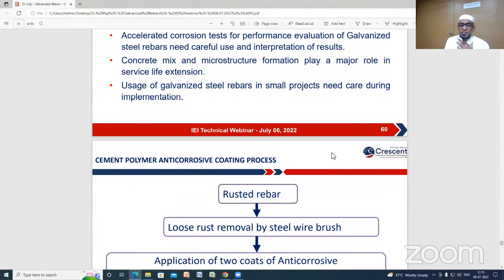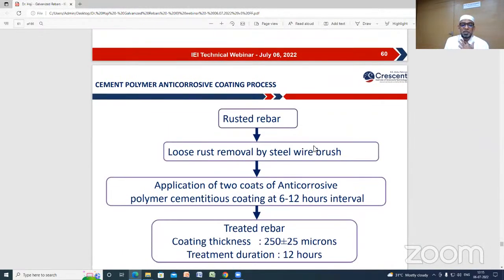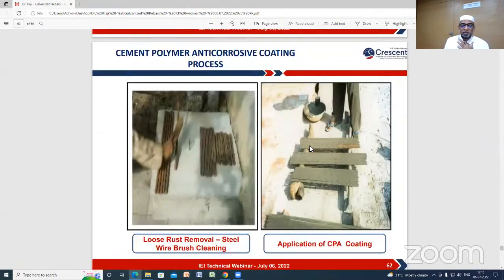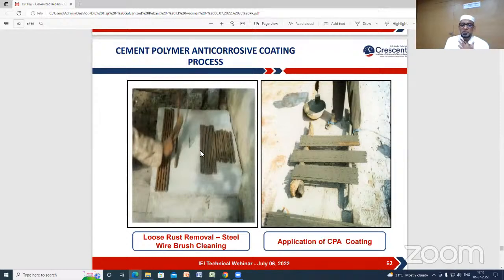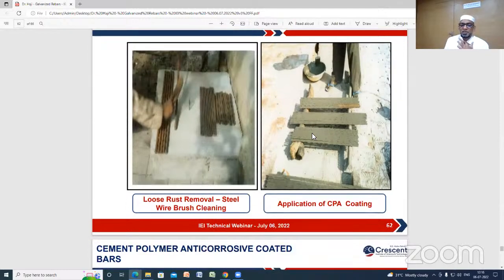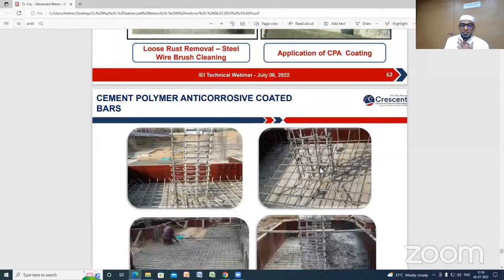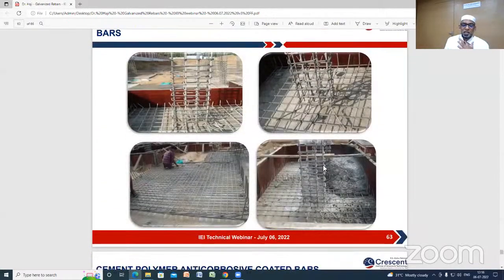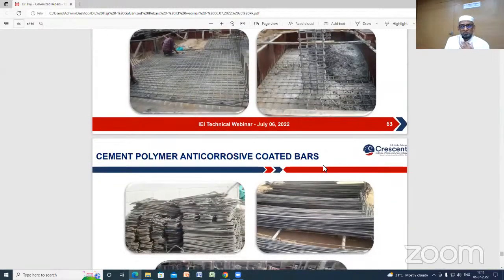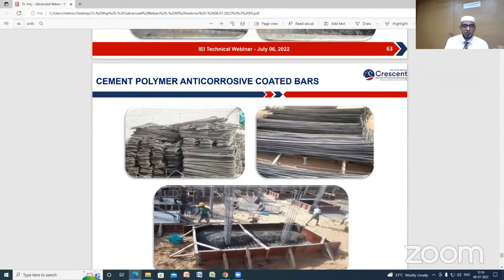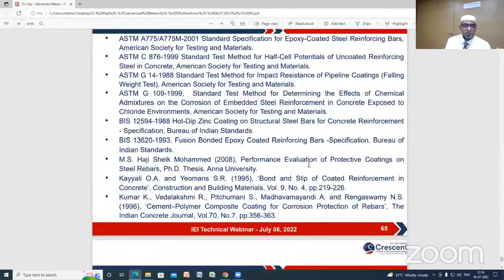So in these types of cases, we can go for a simple anti-corrosion process. We developed an anti-corrosive polymer solution that can be mixed with cement and applied as a coating. This we tested in some residential projects and it is doing fine. In all the possible nooks and corners, we cannot wait for time to adopt things. At every level, we have to take some measures so that durability will be enhanced, leading to sustainability. And with this, I'll wind up.